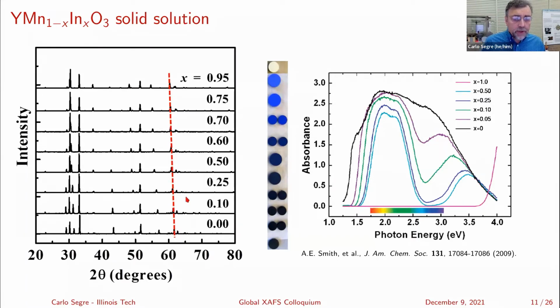So these are the diffraction patterns from the Smith paper from 2009, and these absorbance data, which show an absorbance in the blue, absorbance everywhere but the blue, and there's a dip here where you get this beautiful bright blue color, and it gets a little darker, gets very dark here, and becomes black by the time you reach manganese. And as they point out here, this is a consistent structure. There's slight changes in lattice parameters. They deviate smoothly, but you have the same structure all the way from x equals 0 to x equals 0.95.